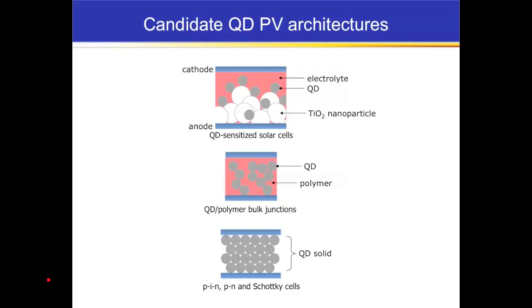Now you can imagine several different ways that you can incorporate quantum dots into a device, and I showed just 3 different ways here. You could make a quantum dot sensitized solar cell. You could make a bulk heterojunction by taking quantum dots and mixing them with a conducting polymer. And there are lots of groups around the world that are working on these 2 approaches. The approach that I'm going to talk about today is a kind of an all-inorganic approach where we just take a neat quantum dot film that we might call a quantum dot solid and sandwich it between 2 electrodes. And the nice thing about this approach is that it's reminiscent of normal inorganic device constructions or geometries.